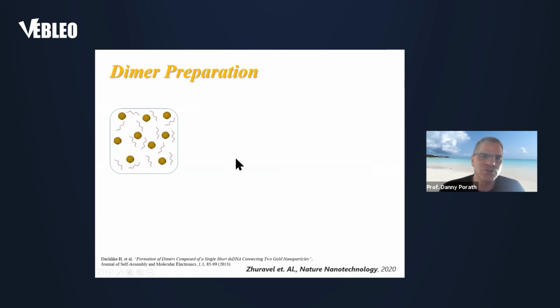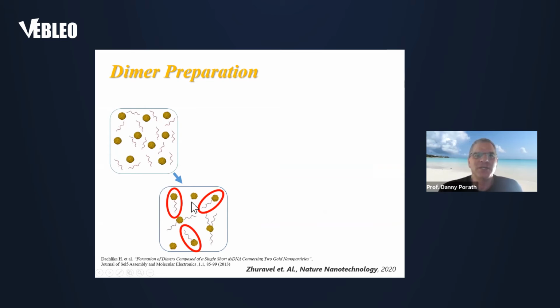So how do we make sure that we have just one molecule? So we mix nanoparticles, in this case, 8 nanometer particles, with 100 bases long single-stranded DNA with a tile in the end. When we mix them, there will be some connections. Some nanoparticles will remain without DNA. In some cases, we'll have just a single DNA strand that binds to the nanoparticle. And in other cases, there will be 2 or 3, and so on. So that's determined by the relative concentration.